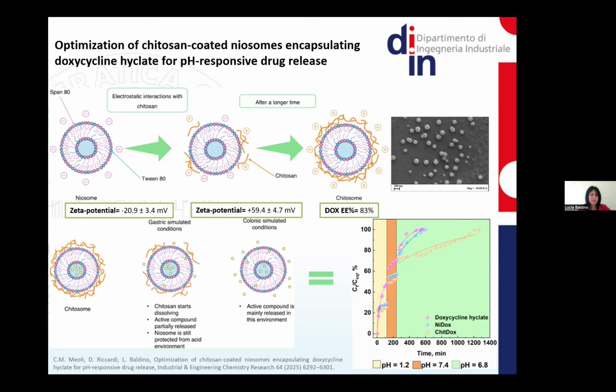Thanks to the electrostatic interaction between negatively charged niosomes and positively charged chitosan. And we checked the proper coating of niosomes with chitosan looking at the zeta potential value. Indeed, it changes from a negative value to a positive value. So we characterized the chitosomes in terms of morphology and other properties. In particular, they showed a regular spherical nanometrical morphology with a mean size around 200 nanometers.